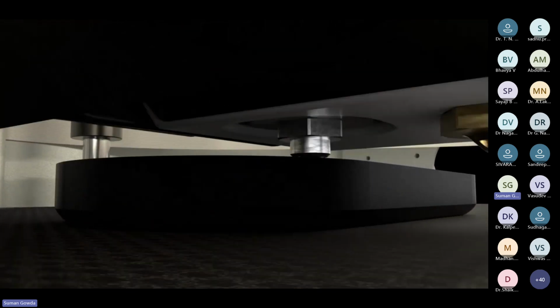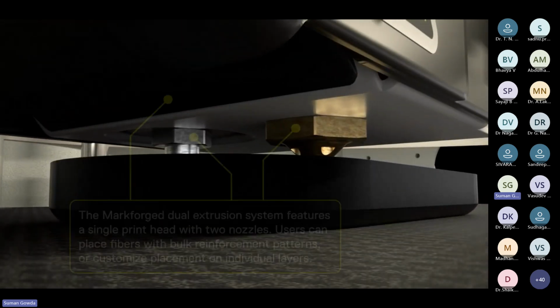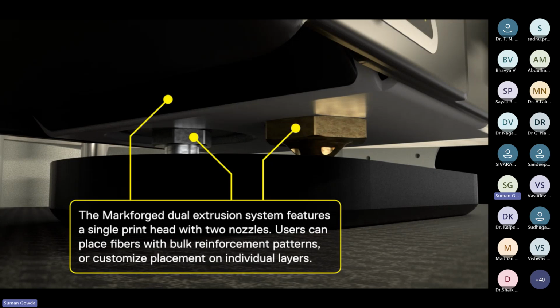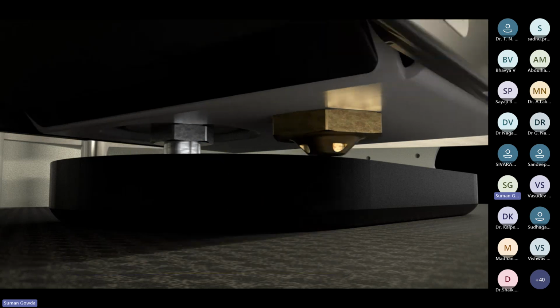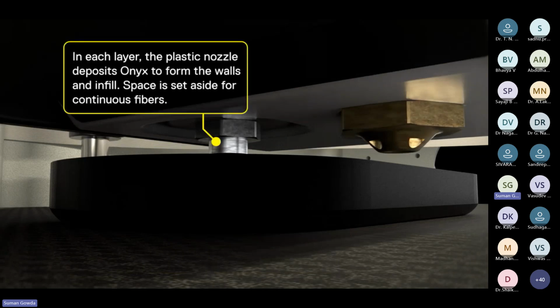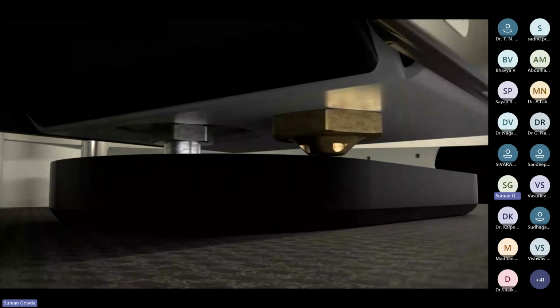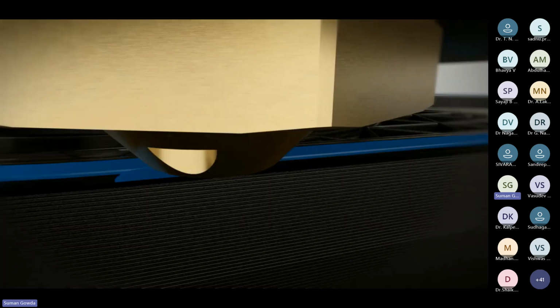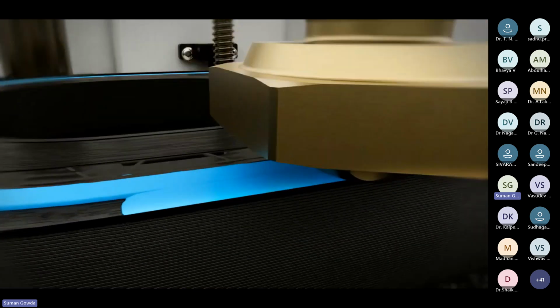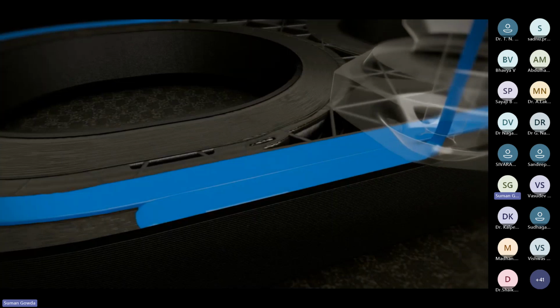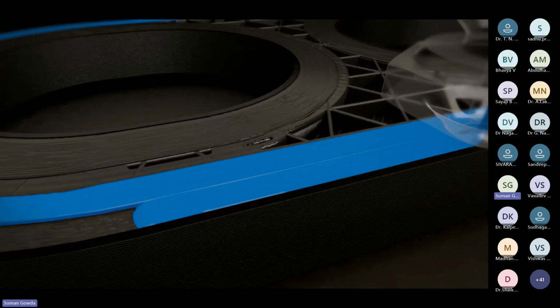There are two nozzles. The nozzle one prints the onyx material, whereas the nozzle two deposits the fiber material. And when it deposits the fiber material, we are not melting the fiber. We are just pressing the fiber on top of a plastic that we had printed as an initial base, so that the fiber gets bonded with the plastic. The nozzle in the back does the job of printing with the plastics, and the nozzle in the front does the job of deposition of fiber. As you can see, it's a circular fiber material, and we are going to press it, and then it's going to turn into a rectangular shape.